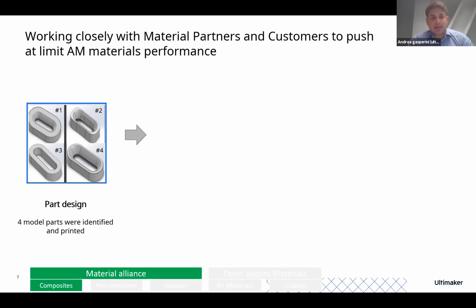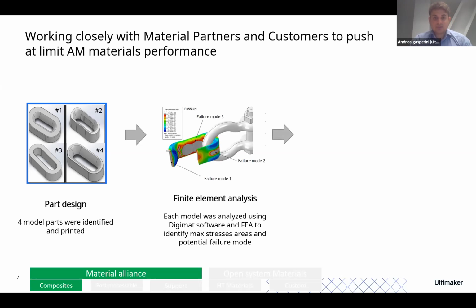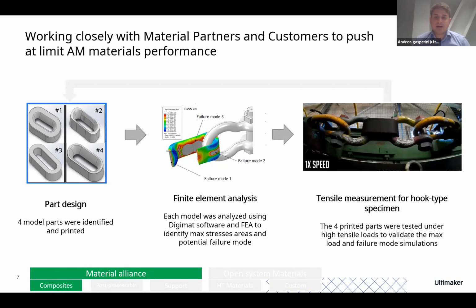So what we did together with DSM was to start deep diving into different types of designs for this type of hook. We created 4 different models, which we analyzed with finite element analysis using Digimat software and the FEA software to identify the area where the maximum stress was occurring and also the potential failure mode per each model. And then we stressed the part in a controlled environment before testing, to understand the maximum load that specific model can withstand. And then, as you can see, we were iterating until the best load specific for that hook was achieved.